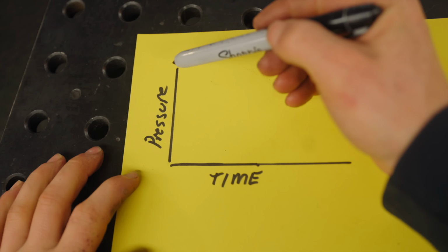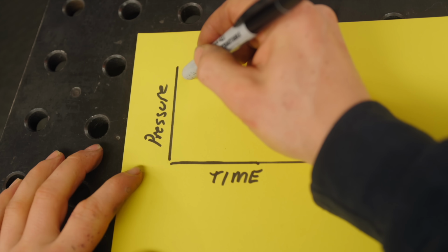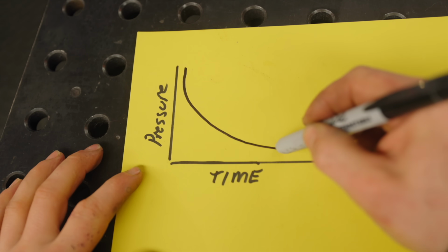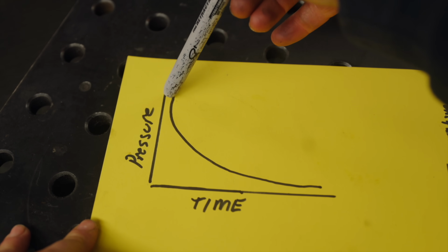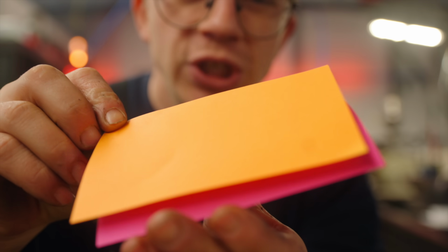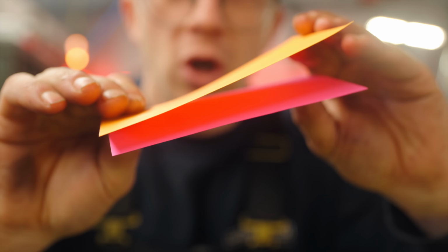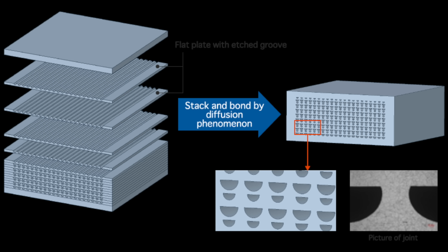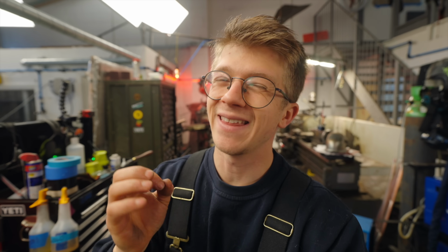We know that if we want to get something to stick, when we have high pressure, we can do it with a low time. At the extreme end here is explosion welding, where they take 2 sheets of material, put explosives on top, and detonate it. Pow! Insane pressure over a very small amount of time. My understanding now is that that's more of an interlocking than a diffusion bond, but at the other end of the extreme is when they're diffusion bonding crazy complex small heat exchangers, and they need the lowest pressure possible in order to get the least amount of deformation.